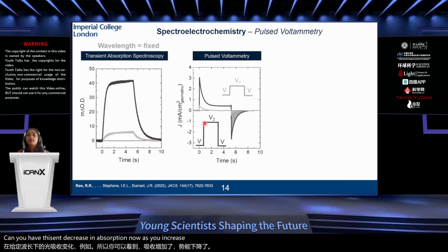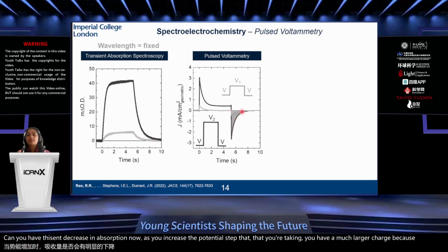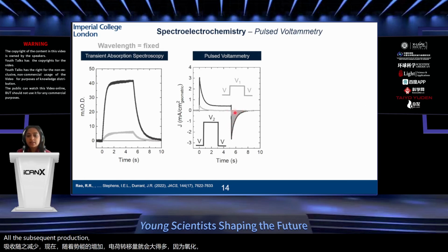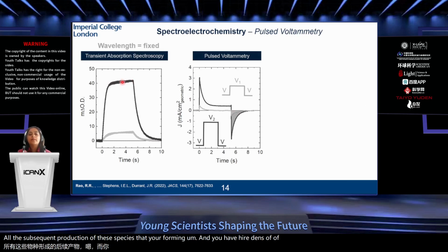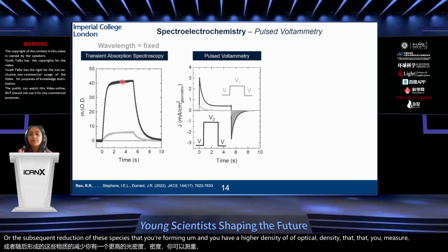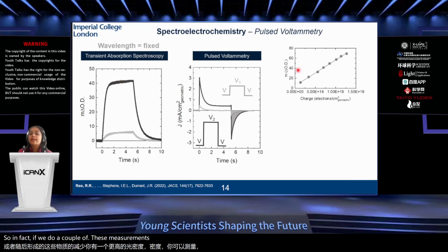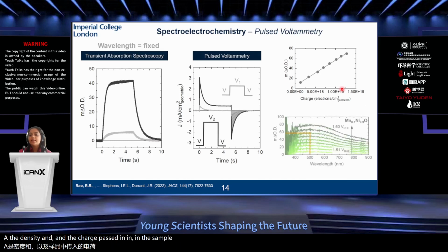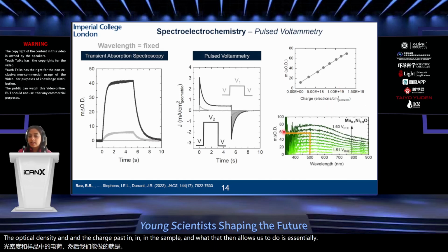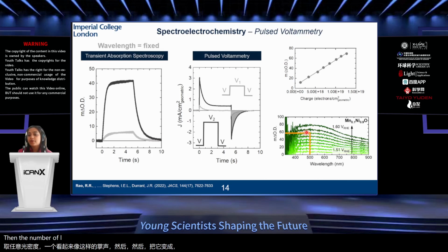Now, as you increase the potential step that you're taking, you have a much larger charge transferred because of the oxidation or the subsequent reduction of these species that you're forming, and you have a higher optical density that you measure. So in fact, if we do a couple of these measurements, what we get is a direct relation between the optical density and the charge passed in the sample. And what that then allows us to do is essentially go to any optical density that we have in a plot that looks something like this, and turn that into the number of electrons per geometric area.